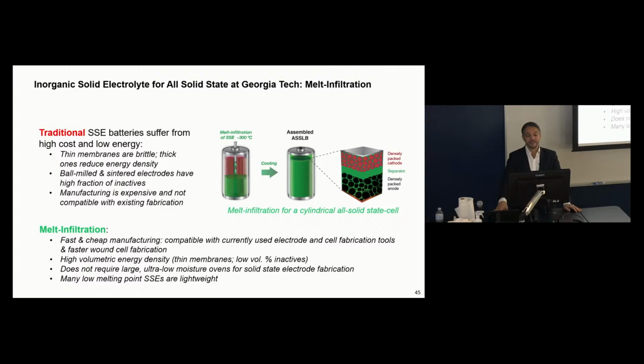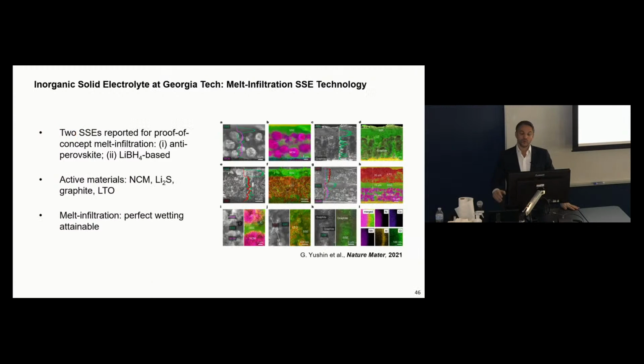And another interesting feature is that these electrolytes that have very low melting point, fortunately, or maybe not fortunately, but actually it makes sense, they're also lightweight. They have low density. So you have a density which is even lower compared to density of liquid material and dramatically lower compared to density of some of the solid electrolytes people are considering, like garnet electrolytes. And so when you have these molten electrolytes, another interesting feature is that you can have wonderful contact between the electrolyte and active particles. So if you have a good wetting behavior, you can wet your electrodes really well, and you can have very low charge transfer resistance.